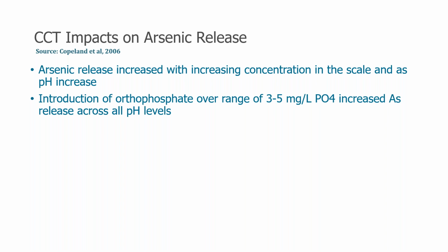Out in the distribution systems, all the arsenic that's on the pipes may tend to desorb as we increase our pH for corrosion control. So that could be an issue in areas that have had a lot of historical arsenic loading and something to look out for. Their findings also found that orthophosphate addition did increase arsenic release because it scavenges and there's some competitive desorption across all the pH levels. So just something to think about, small systems, groundwater systems that may have had a lot of historical arsenic loading and are changing treatment for corrosion control.